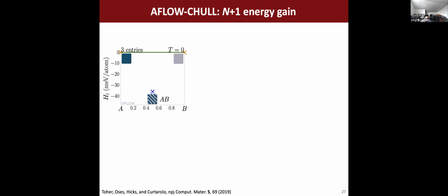I'm going to give you one more example. This is called the N+1 energy gain descriptor. Here we have a plot that I showed you earlier. Remember, we have the tie line here with the pure A, pure B, and then the 50-50 mixture. This distance here, I keep saying it's the driving force for the reaction, but there's another way of looking at this distance. This distance here is also the enthalpy gained from going from materials that have only one component to 2 components. So the question is, what is the energy gained from increasing the number of species, the number of elements in my material?